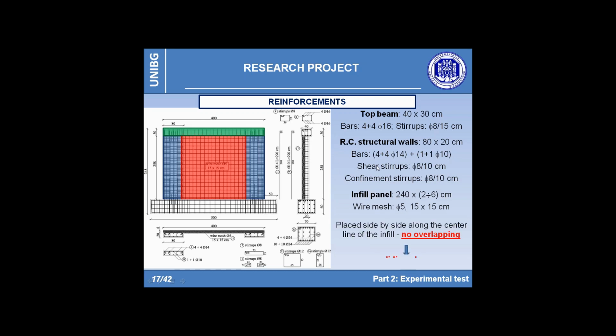It's also important to note that sheets of electrowelded wire mesh are only placed side by side. In this way, the infill results attached to the remaining structure thanks to the wire mesh that goes on only over the structural walls. This layout has been responsible for the mechanism affecting the infill observed during the test. In fact, in correspondence of the shrinkage crack developed in the middle of the infill panel, the central panel tends to divide into two halves.